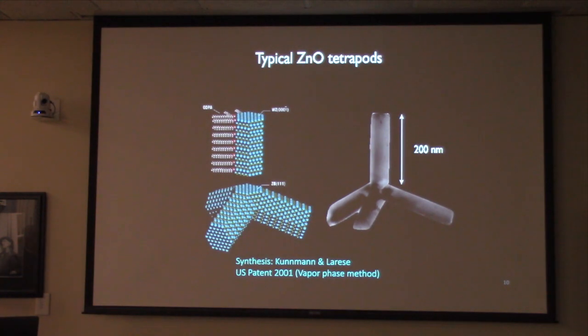So one of the examples that we've been able to do is look at and produce large quantities, because remember, neutrons are a bulk probe, so we have to produce mole quantities of these materials, and we want them to be uniform. And so we've been fortunate enough to figure out how to generate things like these tetrapods of zinc oxide. And then we can deposit things on those, and whether they're tetrapods or rods or plates, they're stable enough for us to deposit, either by solvent-based methods, or now what we're starting to do with physical vapor deposition methods, these particular metal catalysts on them.